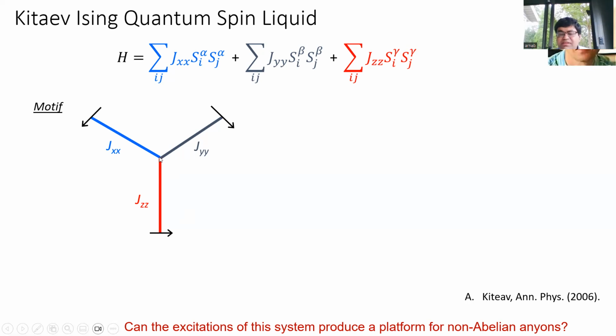What that means is that the spin in the middle is completely frustrated, because the red bond tries to pull the spin in one direction, the blue bond tries to pull the spin in a second direction, and the gray bond tries to pull the spin in a third direction, so that spin is completely frustrated.